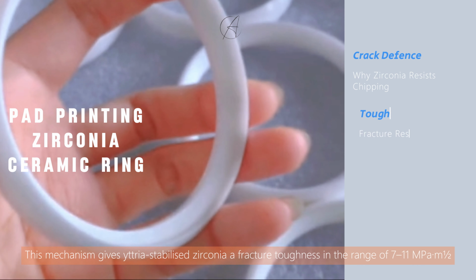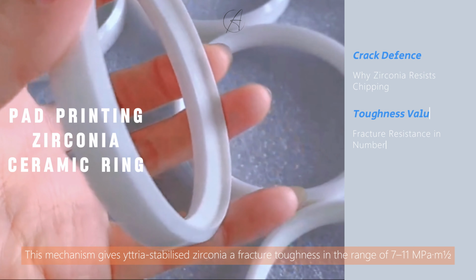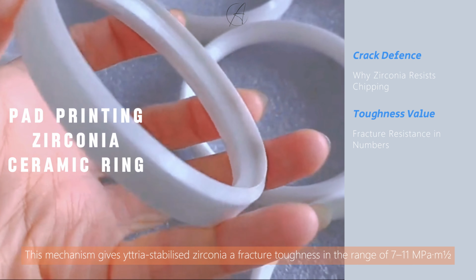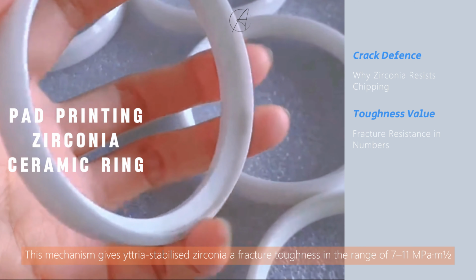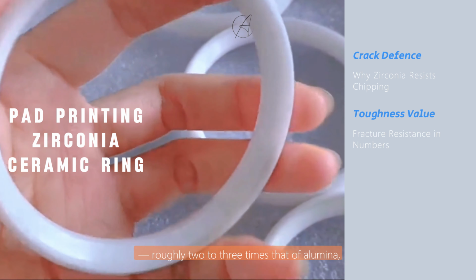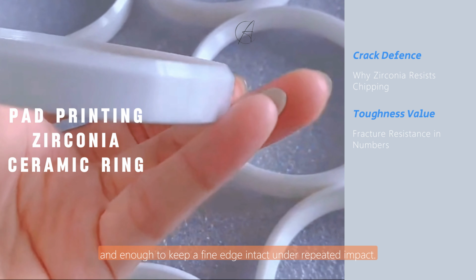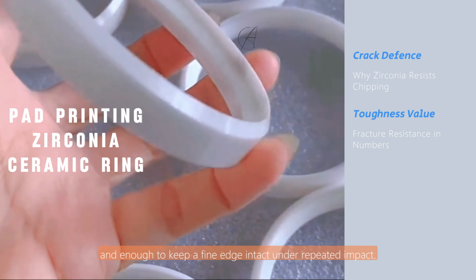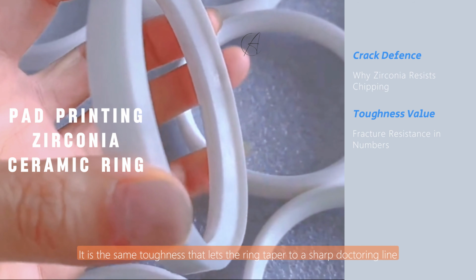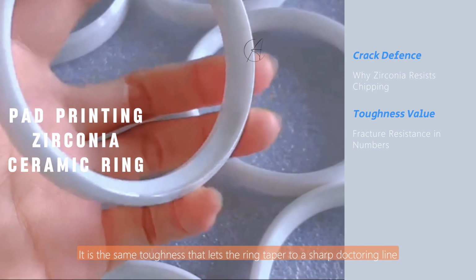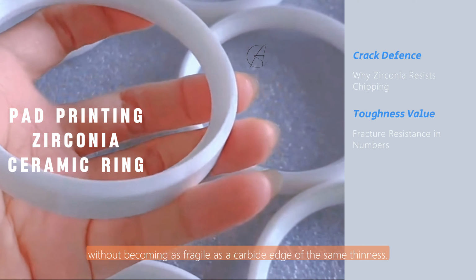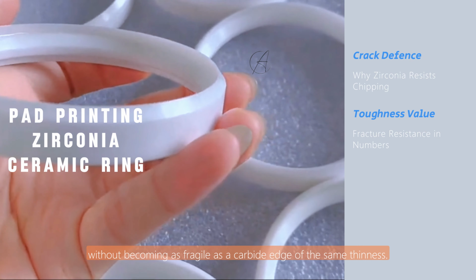This mechanism gives Yttria-stabilized zirconia a fracture toughness in the range of 7 to 11 megapascal-root-metres, roughly 2 to 3 times that of alumina, and enough to keep a fine edge intact under repeated impact. It is the same toughness that lets the ring taper to a sharp doctoring line without becoming as fragile as a carbide edge of the same thinness.